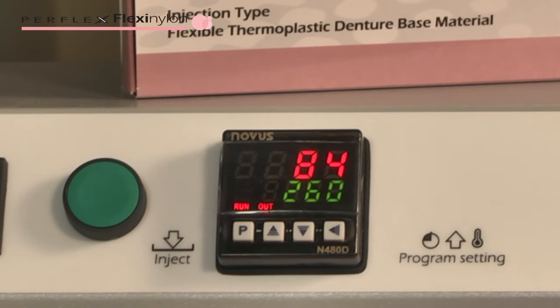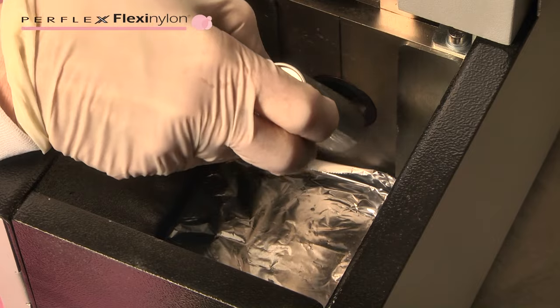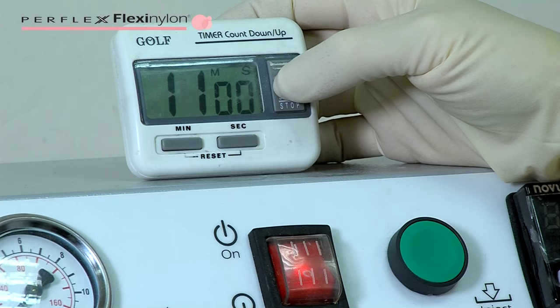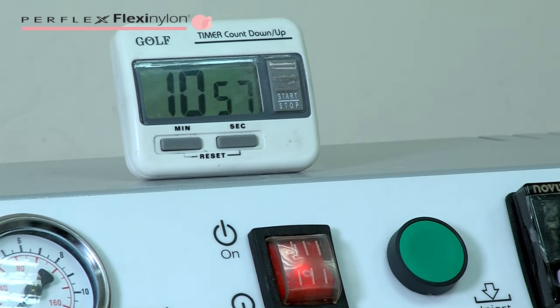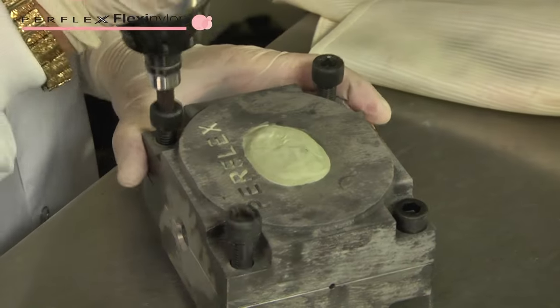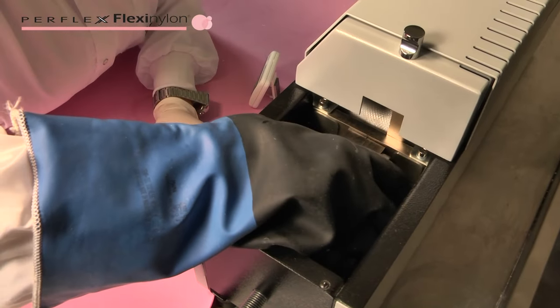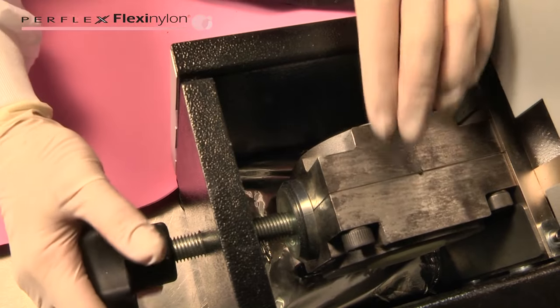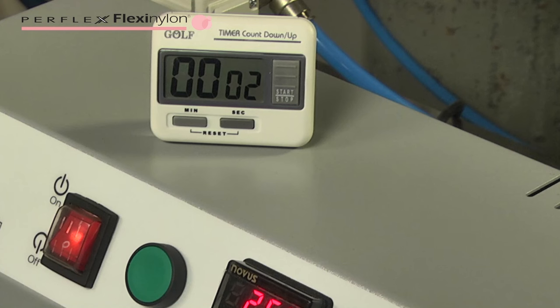When the furnace reaches 260 degrees Celsius, insert the lubricated cartridge tube with its cap facing outwards into the furnace and the stamped part inside. Press to start the external timer for 11 minutes. Close the flask with 4 screws manually or with a pneumatic machine and place into the injector machine. Place the closed flask into the injector 5 minutes before injection. Close the handle gently and close the safety protection door. When the external alarm sounds at 11 minutes, press the button to inject.